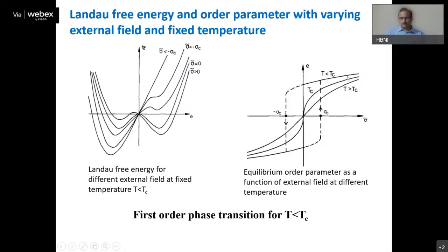If you go from this direction, you can see the order parameter has some value like this. And if you go from the other direction, the order parameter has some value like this. So you have two critical field values in order to have this phase transition. This hysteresis is clearly a signature of a first order phase transition. Of course, here I am considering the case where the order parameter is symmetric about the free energy. It means minus E and plus E, both values are possible.